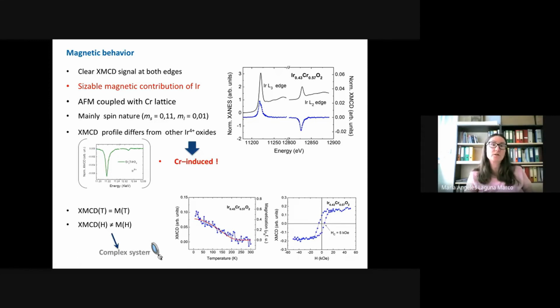And this is very interesting because it's very different from the typical large orbital magnetic moment found on iridium 4+ oxides. An example of this is found here in green. You can see that the XMCD signal is very different, showing a different character of the magnetic moment. In addition, this suggests that the magnetic moment of iridium is induced by chromium, which is quite a remarkable and surprising result for an oxide.